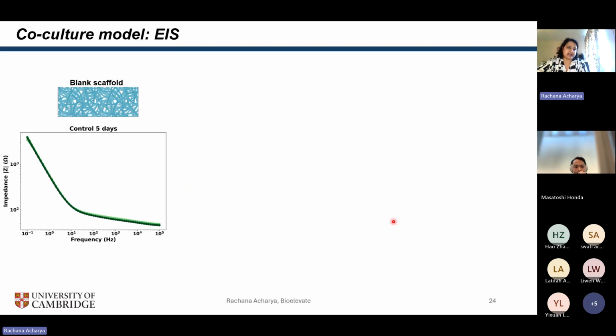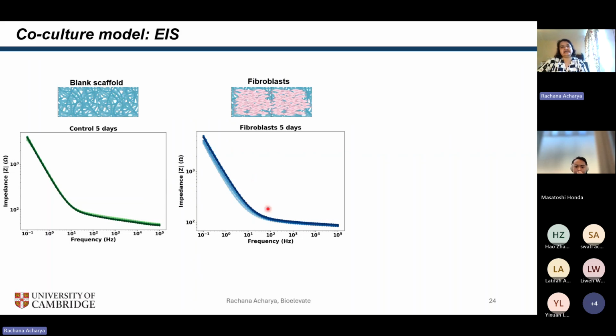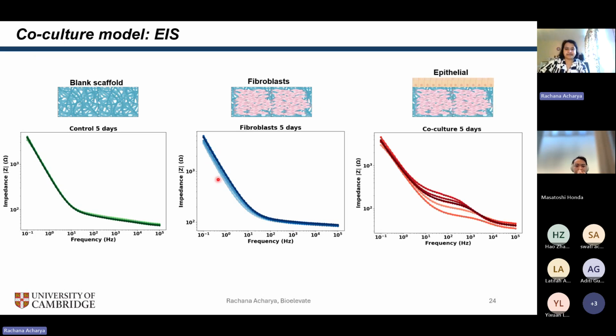But that's fine because we can use our second method, which is electrochemical impedance spectroscopy, which I'm sure all of you are aware has been done for multiple models and is a trusted technique to look at barrier growth, to actually look at the formation of this barrier. So again, starting with a blank scaffold, we have a mostly reproducible and consistent EIS curve. Once I start growing the fibroblasts, I again see that it's mostly constant. The only change I can notice is in the capacitive behavior, which also makes sense, as the cells are growing, there's a capacitive shift in my impedance. But very interestingly, once I put down my epithelial cells, I see that there is this large change in the impedance, especially in the mid-frequency regime.